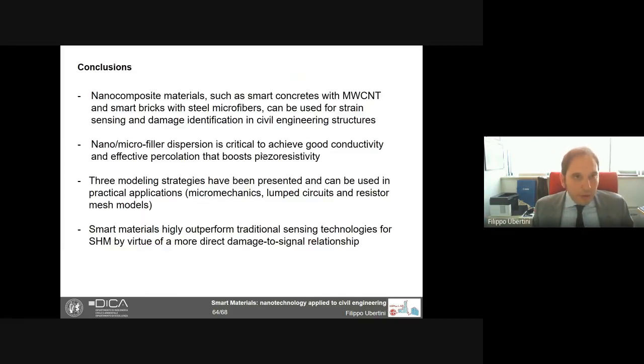So let me conclude this talk by saying that nanocomposite materials such as smart concretes with multi-wall carbon nanotubes and smart bricks with steel microfibers are very attractive materials for the future of structural engineering. They can sense the strain, and they can allow damage detection and localization. It's very critical to disperse the nano or micro filler in the proper way, because otherwise we do not reach the percolation and we lose what we are looking for.